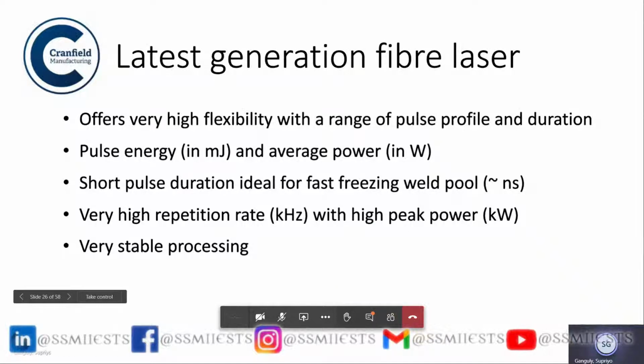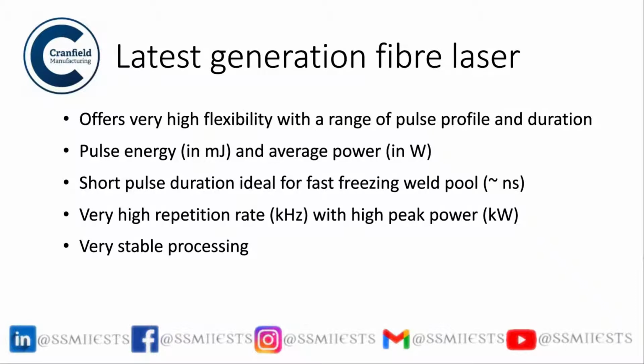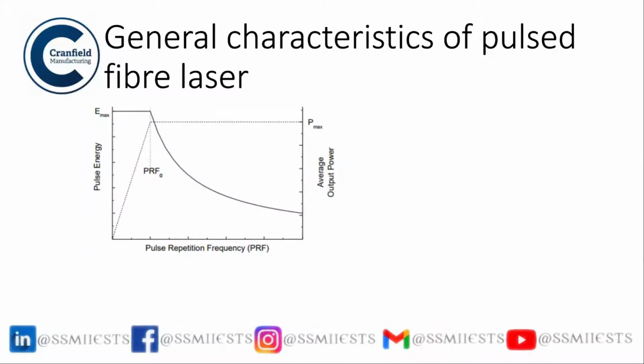I will now talk about some applications, battery applications actually, in e-mobility, where I will talk about joining of copper and steel. The latest generation fiber lasers offer very high flexibility and a range of pulse profiles and durations. Pulse energy and average power can be controlled very well. Short pulse durations are ideal for fast freezing, which is important for dissimilar joining. With very high repetition rates, you can have a reasonably high peak power and a reasonably high average power, and it gives you very stable processing. All these factors made it a very good tool for dissimilar joining.